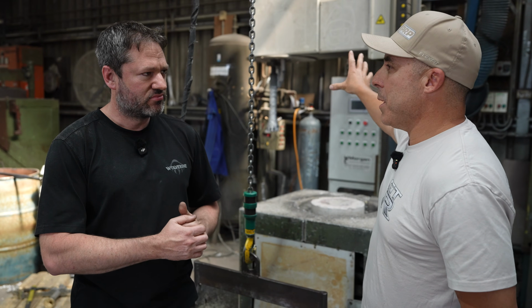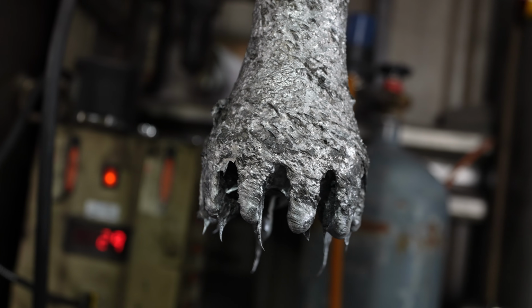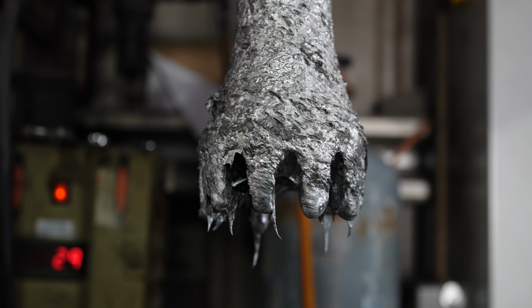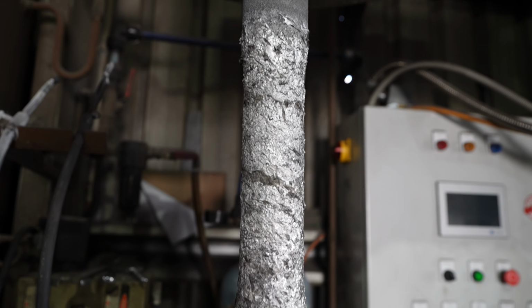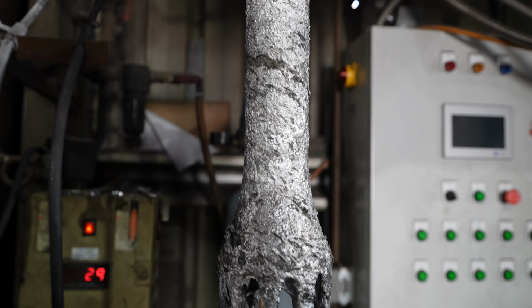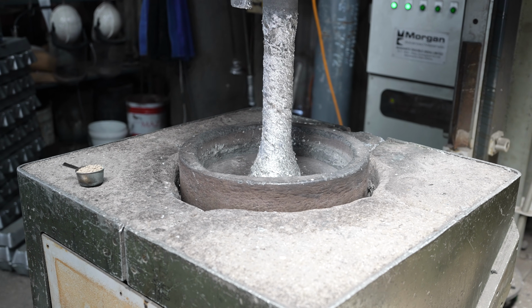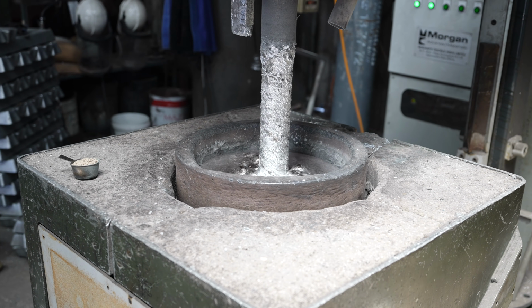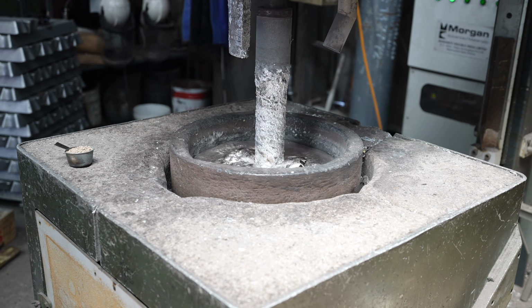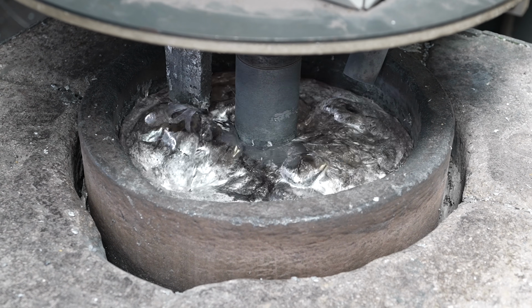I want to talk a little bit about this machine because this is one of the reasons why we prefer to work with you specifically at Hasco and are leading the game with Australian manufacturing on a global level. So the way we treat our metal, or aluminium in particular, is we degas the metal, and the way we do that is by pumping nitrogen through the metal. And the reason we do that is it removes impurities, it removes oxide films that form as part of the molten metal process, and it also removes hydrogen, which is absorbed from the atmosphere.